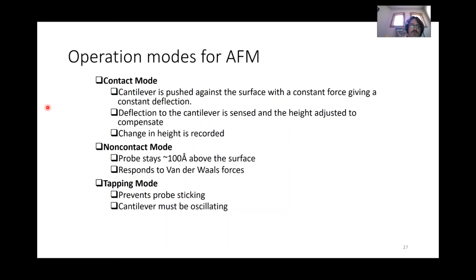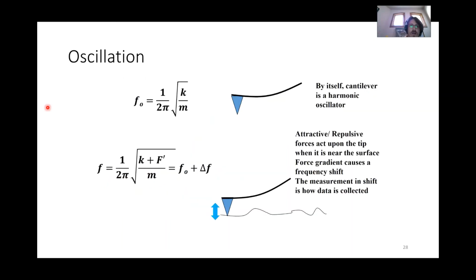Tapping mode prevents probe sticking, and so it's actually oscillating. You're oscillating this probe, so it's a harmonic oscillator. I won't get too much into these, but by itself, the cantilever is a harmonic oscillator. Attractive and repulsive forces are acting upon the tip when it's near the surface, and there's a gradient to this force, and it's causing a frequency shift. The measurement of that shift is how data is collected, basically. I may go into more detail on this, I may not, just because we have a lot of topics. But the cantilever is a harmonic oscillator.